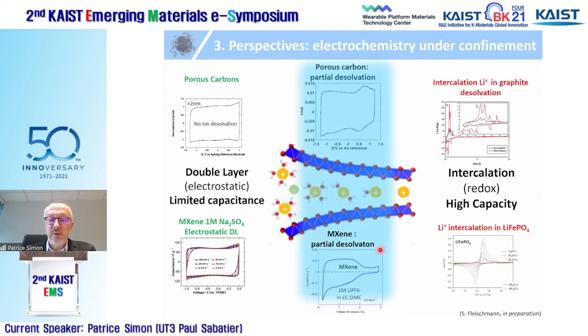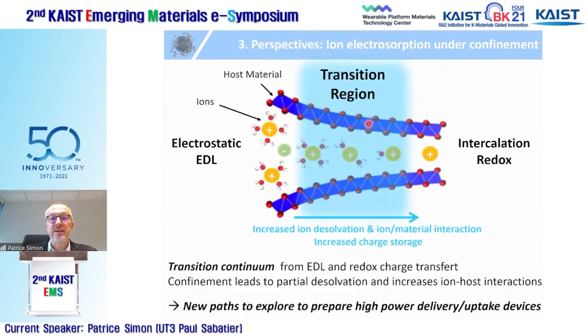And I just showed you that when we have this kind of partial desolvation in MXene, we move from this situation of double layer to this situation where we increase the capacity but still preserve high power. This situation fits exactly in the middle, in the zone between these two charge storage processes. Similarly, with porous carbons, we showed a couple of years ago that when the ion size is more or less close to the pore size, you can see a set of redox peaks appearing here, but there is no formal redox change of the carbon. It's just an increase of electron transfer between the ion and the carbon. So these processes, where ions are partially desolvated between layers of 2D materials, can be seen as a transition region between electrostatic charge storage and full charge transfer via intercalation redox.